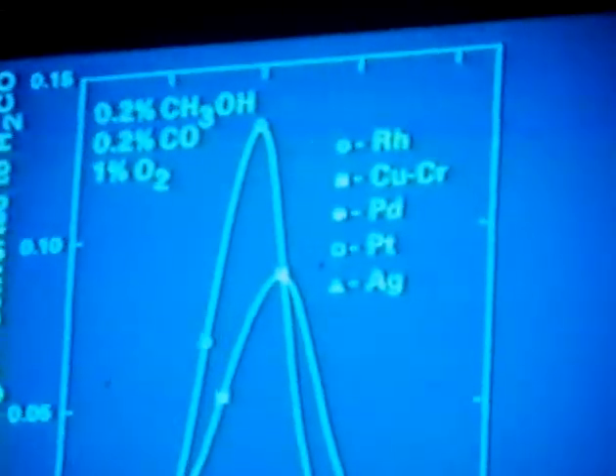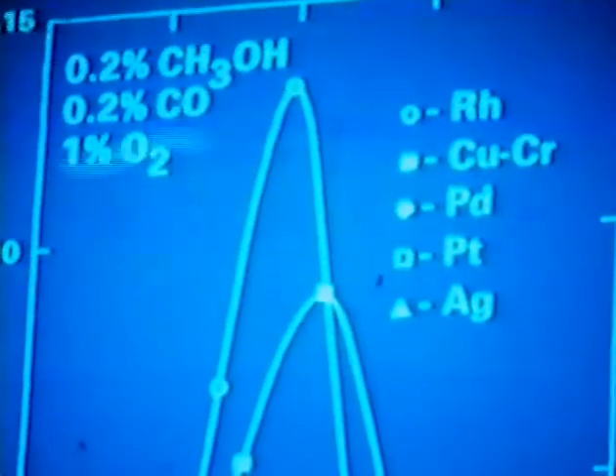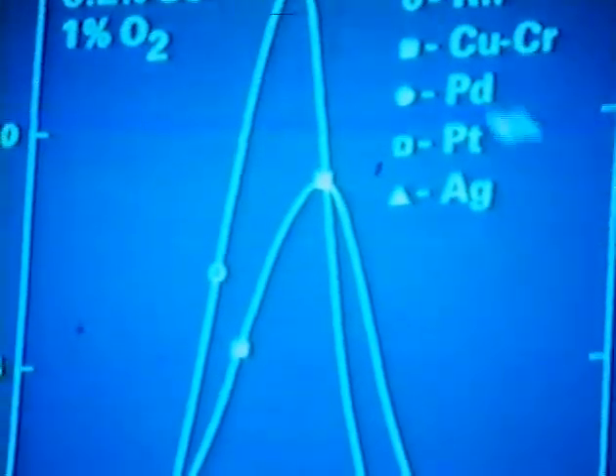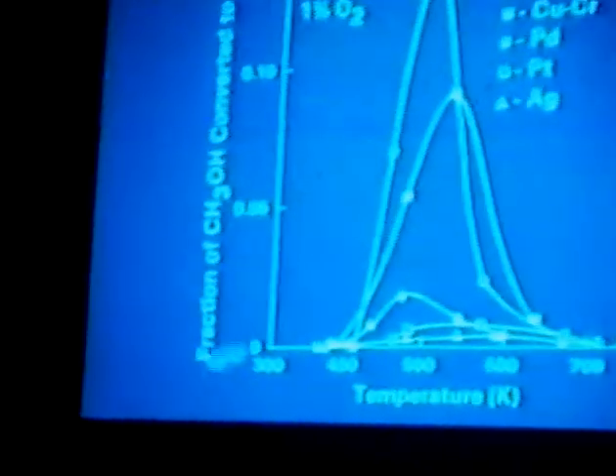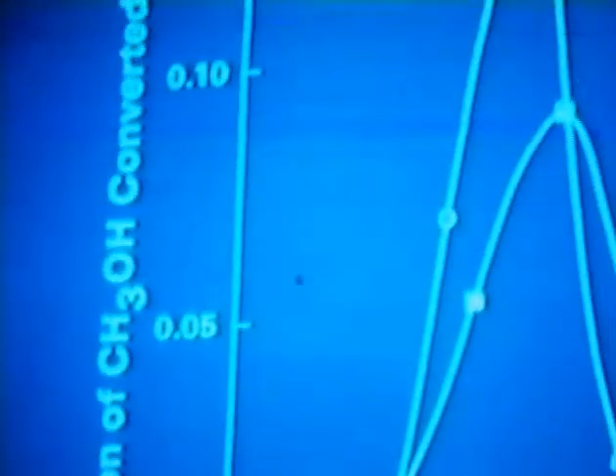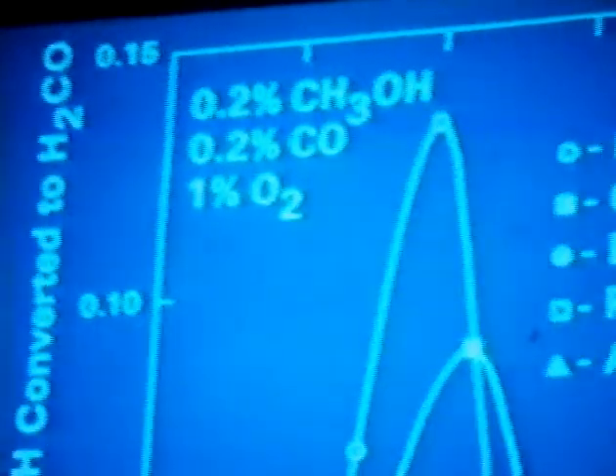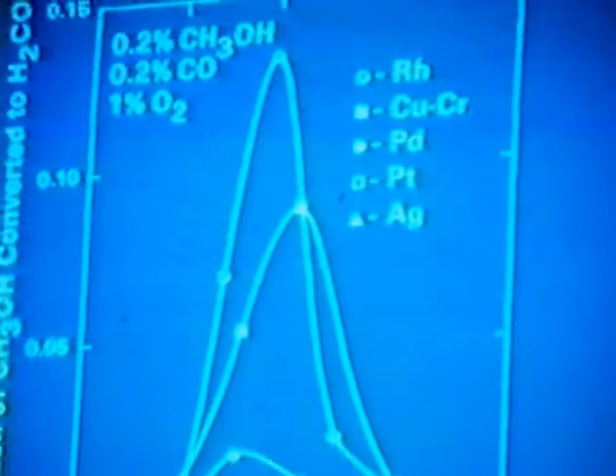And in fact, in this next slide here, I can give you an example of what we see for various catalysts. Here we show results of formaldehyde production over 5 different catalysts. These are all supported on gamma alumina, as are all the catalysts that I will speak about today. A couple things to note. What we're doing here is in the laboratory, we're reacting methanol, CO, and oxygen over these various catalysts and looking at the formaldehyde yield as a function of temperature. What you see here is that the yields of formaldehyde are quite different for these different catalysts. And in fact, this indirect production of formaldehyde can be quite extensive given the large emissions of unburned fuel that are characteristic of these cars.